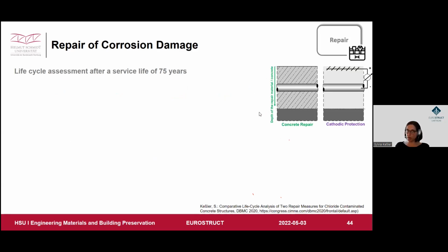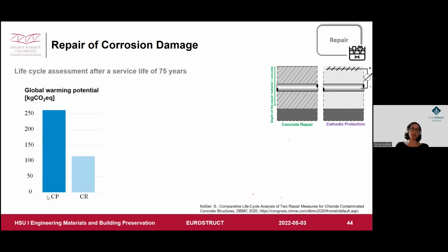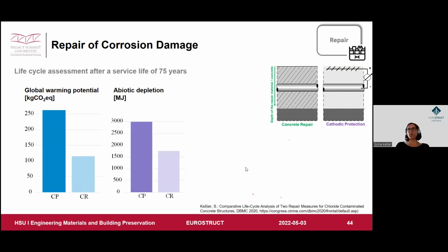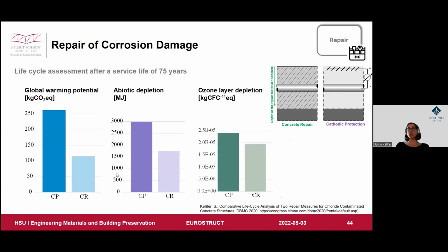Here we have a concrete repair, so total replacement of the chloride-contaminated or carbonated concrete, in combination with the cathodic protection system, where you apply an external anode, you establish an electrical connection, and then you apply a current from the outside to prevent the reinforcement from corroding. And you would guess cement and concrete have such a high carbon footprint. Now think about which of those methods you would guess has the poorest carbon footprint. You will probably be surprised, because here we wanted to ensure a service life of 75 years. And we compared the global warming potential of the cathodic protection system with the concrete repair system, and in at least 3 of the sustainability indicators, the cathodic protection ended up much worse with its carbon footprint than the concrete repair. So keep in mind, cement must not always be the least sustainable.